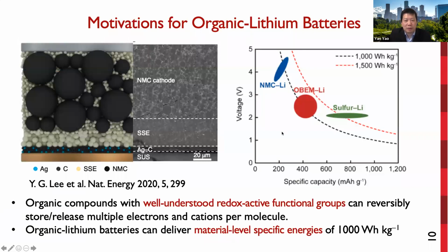I hope to see more details on how QuantumScape was able to accomplish this in the future. The leading cathode materials for all solid-state batteries are mainly nickel, manganese, cobalt oxide, short for NMC. So even if solid-state batteries can work well, the cost of the battery would still be high due to the nickel and cobalt used in these cathodes. To make cobalt-free and nickel-free cathodes and reduce the cost, we propose using organic electrode materials, which are made of carbon, hydrogen, and oxygen, without any transition metals. Organic compounds with well-understood redox-active functional groups can reversibly store and release multiple electrons and cations per molecule. So organic lithium batteries have the potential to deliver material-level specific energy over 1,000 watt-hour per kg, placing them in the same category as NMC lithium and lithium sulfur batteries.